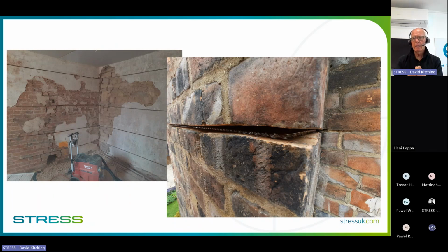But what I wanted to point out here in that right-hand photo was, if you go to site, whether you're familiar with masonry reinforcement or you're not, and see it installed, we've seen some horror stories. It's got to be put in right, otherwise there's no point in doing it. So here you can see just how clean that cut is. We have removed all the mortar. This mortar's normally pretty weak stuff. So if you're going to use it to spread stresses, it's going to have to bond to something, and if it's friable, it's not going to distribute any stresses through it. So you remove all the pointing over the depth you need it. Something like this, you take out around 20 to 25 mil of mortar.